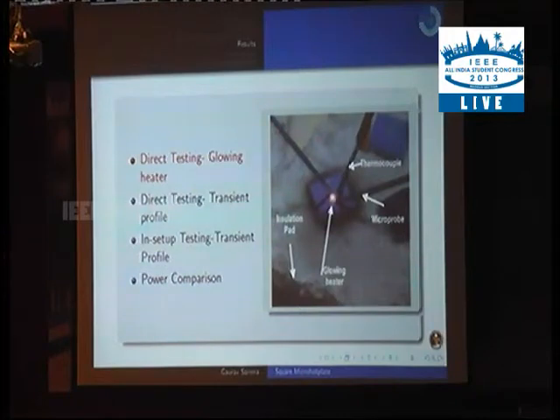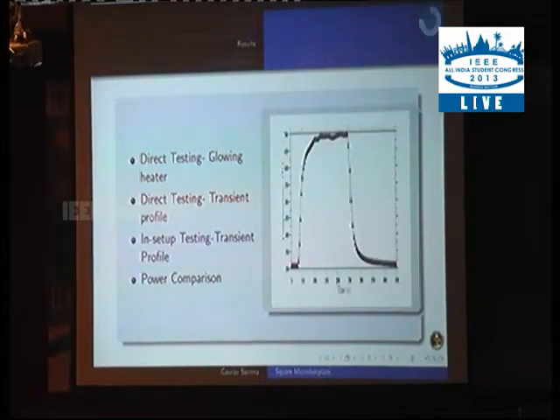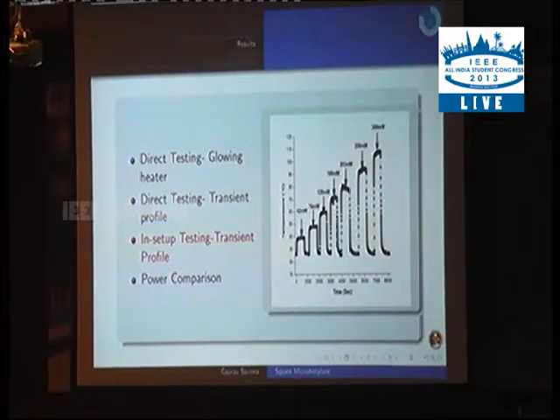Then a few results. Before testing this die on our testing setup, we did a direct testing on the die itself using microprobes. With 175 milliampere of current, this heater is glowing. The temperature here is 700 kelvins. But when we did the testing on the test setup, because of the silver epoxy contacts, which have very low current carrying capability, the highest temperature we could get was 380 kelvins.